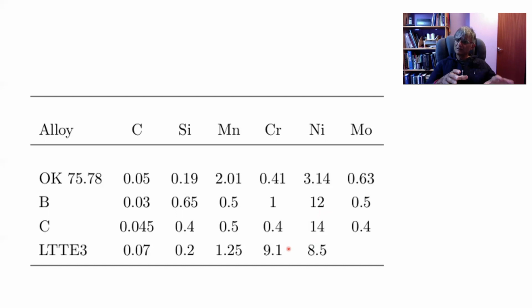But we are working with very small quantities of experimental alloys, and therefore we need and have access to slightly more sophisticated facilities, which also allow us to monitor simultaneously and accurately the phase transformation behavior. And that, of course, is the X-ray synchrotron, which is a high energy X-ray beam. We go to a synchrotron facility and attach a thermomechanical simulator on it, effectively like a dilatometer.